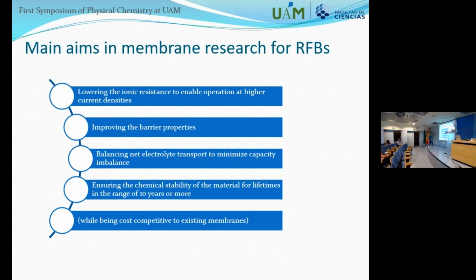So, well, the main aims of membrane research, based on all the things that we saw, are the lowering of the ionic resistance to enable operating at higher current densities, because of course the higher the conductivity, the better will be the performance. We can go to higher current densities operation. To improve the barrier properties, because as we saw, there are many ways, but still the crossover of the ions has to be improved, to stop the crossover of the ions, balancing the net ion transport to minimize the capacity imbalance, and ensuring chemical stability of the materials for very long times, since we want to store energy for a lot of hours, days, weeks, even years. It's the idea of this technology. And all of this while trying to be cost competitive with existing membranes.